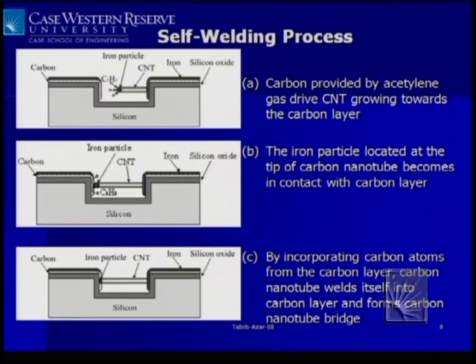So you expose this to the carbon-carrying gas, and as it comes, the carbon and hydrogen get dissociated, and carbon gets dissolved inside the iron, and it saturates it, and then the carbon ends up near the tip, and that starts growing the carbon nanotube. This is a pretty accurate model, by the way. People have done this inside transmission electron microscopes, and there are videotapes out there. If you just Google carbon nanotubes, you will see these video clips, and it really grows very nicely.